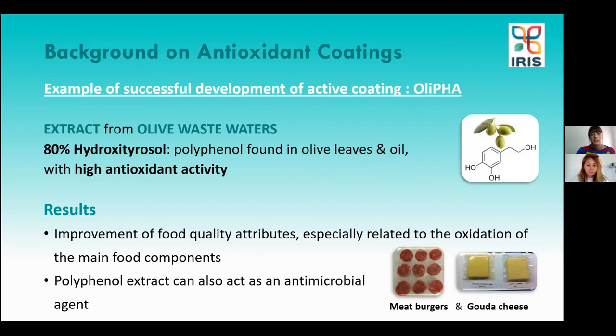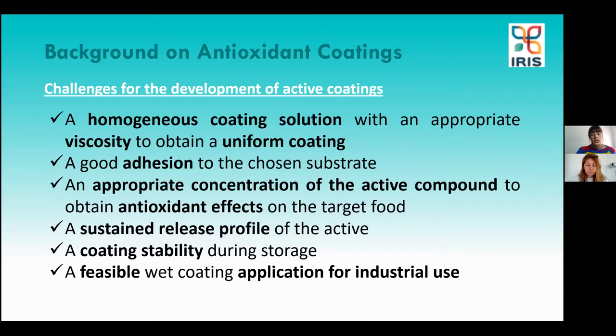Polyphenol extract can also act as an antimicrobial agent. To develop both active liquid solutions and dried coatings, we need to achieve several parameters and find the right balance: a homogeneous coating solution with appropriate viscosity for a uniform coating, good adhesion to the chosen substrate, an appropriate concentration of the active compound, a sustained release profile, coating stability during storage, and feasible wet coating application for industrial use.